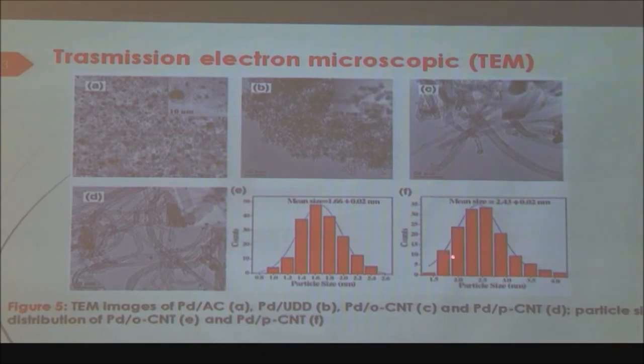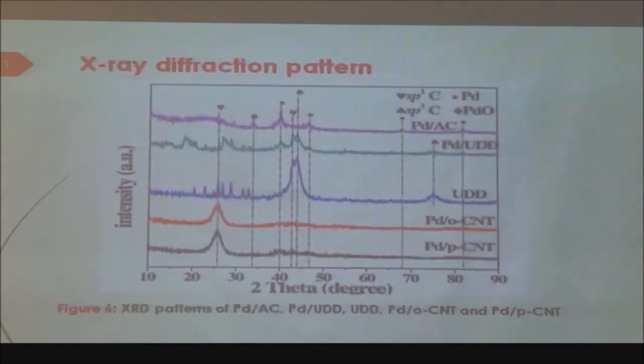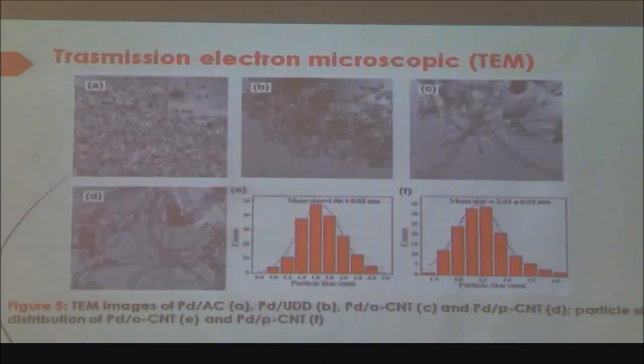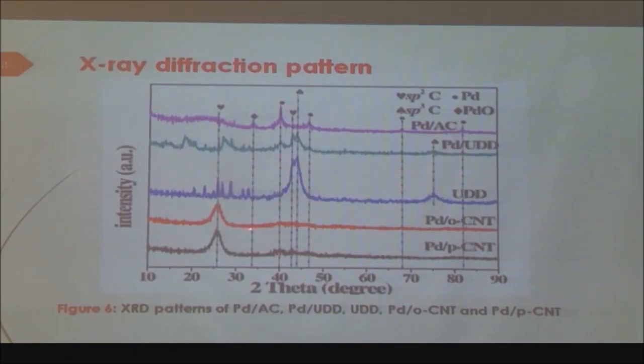study what type of metal nanoparticles have been deposited on it. Once we know it, we characterize it with XRD also. Here we can get information, for example, about what type of sp2, sp3 carbons or palladium, the state of palladium, whether it is palladium metal or oxidized palladium present on the surface. We come to know that a small amount of palladium oxide is also present. We haven't used it, but still it is there on the catalyst. Because we are heating it, and whenever you stop your reaction and remove it into the air, a small amount of air always gets absorbed onto the surface, and somehow this leads to the formation of palladium oxide, which is unavoidable.